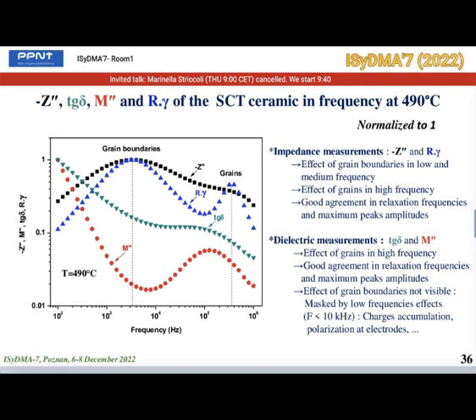frequency evolutions of minus Z second, tangent delta, M second, and R gamma of the ceramic at 490 degrees Celsius. They are normalized to 1. The evolution of minus Z second and R gamma obtained from impedance measurements clearly show grains contributions at high frequency and grain boundaries ones at low and medium frequencies with good agreement in relaxation frequencies and maximum peak amplitudes, while the evolutions of tangent delta and M